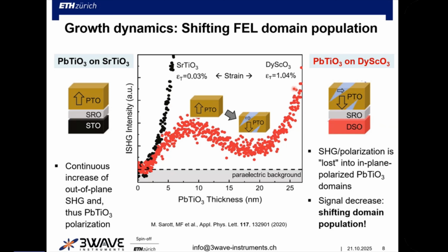So when you do this after you grow your film, you just see it's multi-domain. How did it happen? When did it happen? You don't see. But here you really see it happens here at the, let's say, 5th to 10th monolayer. And knowing that, you can either stop the growth or you can do something against this multi-domain flips. So that's really a power of the technique. It's in situ, not afterwards.